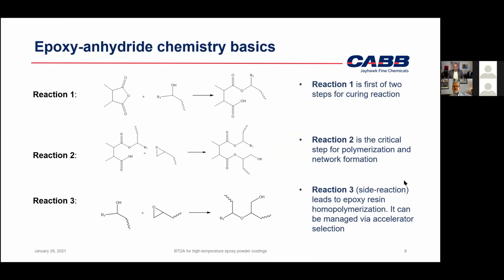Very quick look at the chemistry of the epoxy anhydride curing. So generally it is accepted that there is a two-step reaction process for the cross-linking between an epoxy resin and an anhydride functional curing agent. We have reaction 1 and reaction 2 here, showing that two-step cross-linking reaction. And then reaction 3 is simply the epoxy resin homopolymerizing with the help of some impurities or other things, but this homopolymerization reaction can take place in the absence of the dianhydride. And this reaction is actually quite important for us to understand.